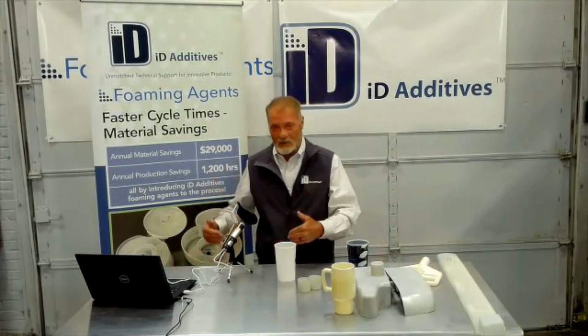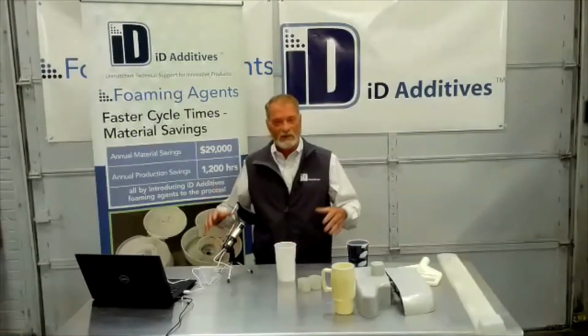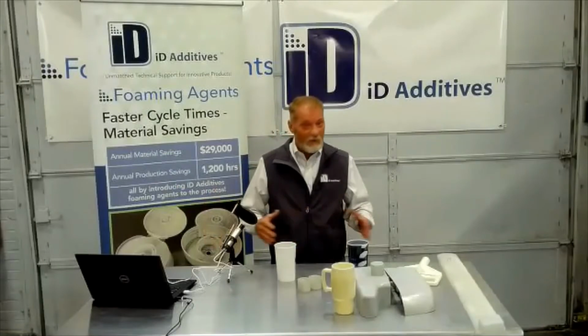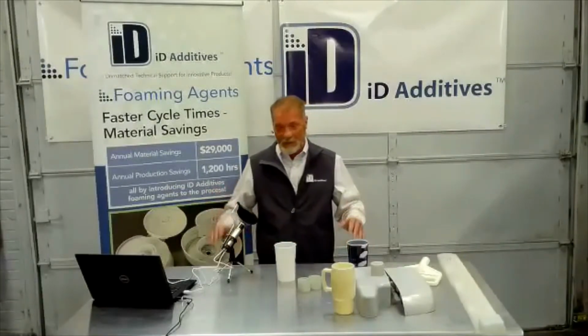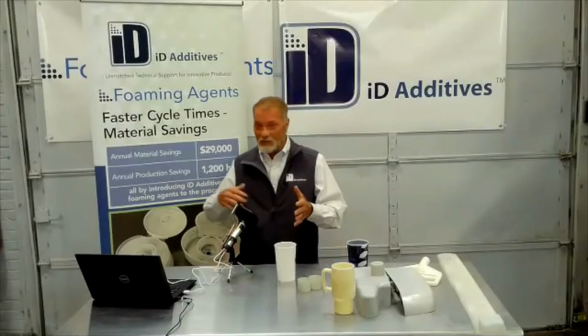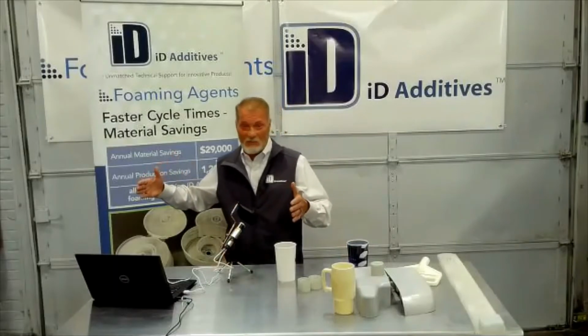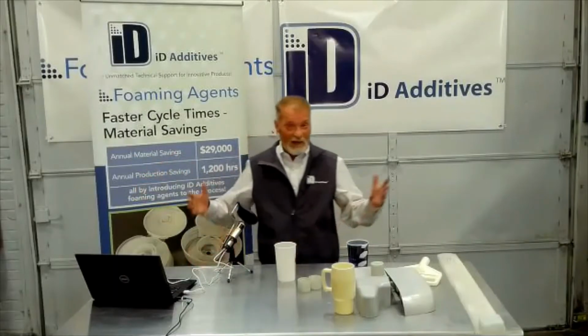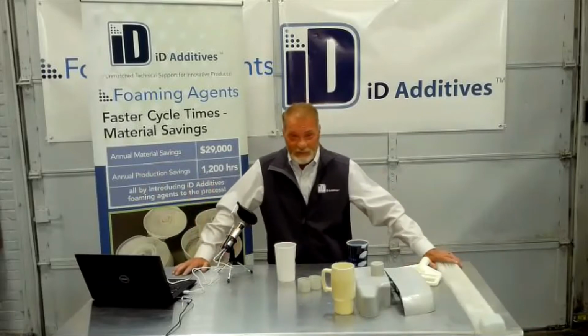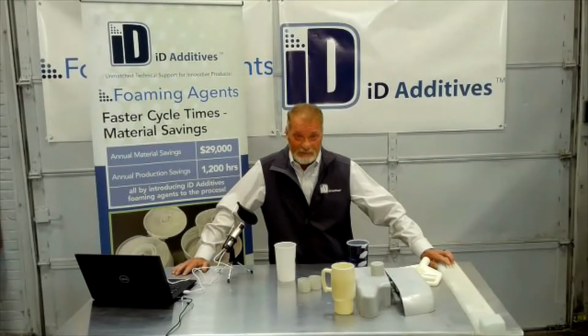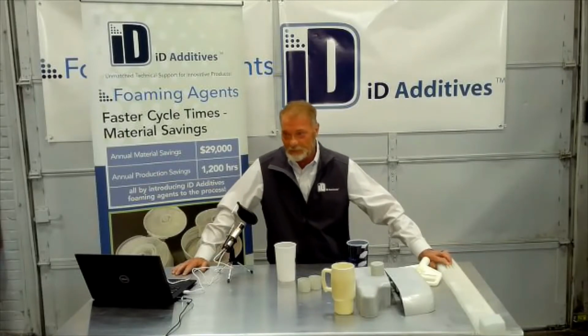Pull heat out of the barrel, control the bubble, get it in quick, let the foam pack the part out, keep the residence time tight, slow the RPM down so it gets back just before the mold opens, inject fast, and that's basic foam process. Temperatures change, it only depends on what they're doing.